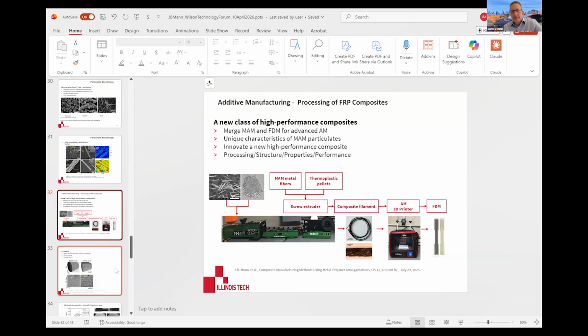And this slide just shows a simple laboratory framework. We take metal fiber and combine it with thermoplastic pellet. We extrude that into a composite filament, and then we 3D print, in this case, tensile test samples or any sample we prefer to produce.